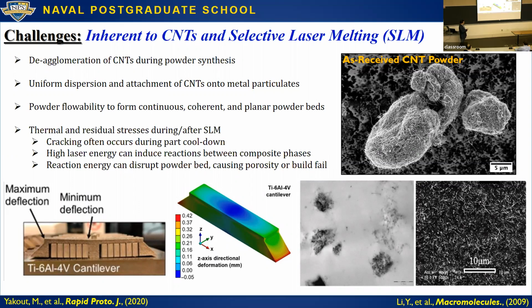But they come in this agglomerated state. So one of the biggest challenges to using them in a composite is we need this to be dispersed. We want it to be uniformly dispersed, as opposed to clumps; essentially a connected network of fibers would be the ideal structure. As far as 3D printing goes, I mentioned earlier that each individual layer is very similar to just a single weld, and you actually get very high residual stresses. So that's kind of an interesting challenge to deal with.